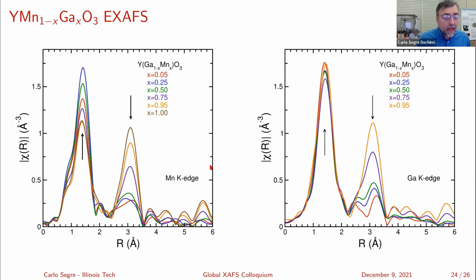So the EXAFS is here, and again, you can see that there are certain trends that are consistent with the oxygen peak increasing here, this one decreasing the same way with the gallium on the gallium edge. Again, we haven't done a full analysis of this yet. I'd rather have better samples first. And I really have to have some rapid thermal annealing, I think, to do this right.